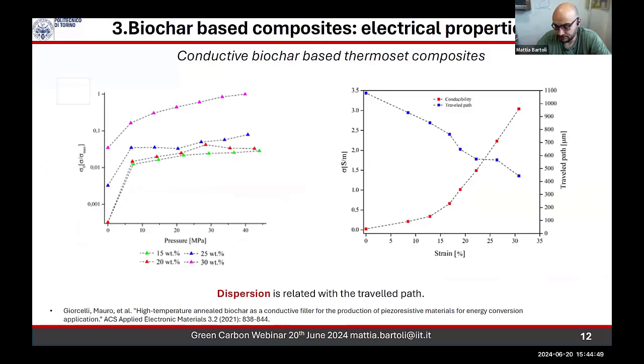Of course, this lies in a proper physical explanation, in particular the available travel path. Micrometric particles means that you can create bridges, as I said earlier. And these bridges, as you can see here, follow the opposite trends of conductivity. You create a preferential pathway in your composite with your biochar particles on the micrometric scale. And this is one of the great things that you cannot do with carbon black.